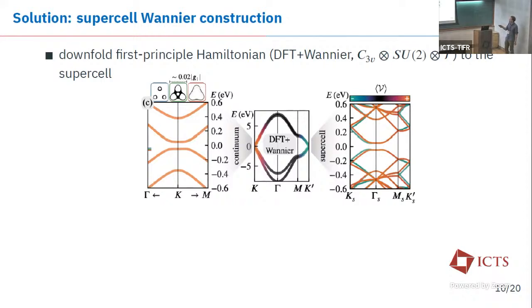So we have rotation symmetries, spin symmetry, and time reversal symmetry, and we just plug them onto the supercell. We get out, compared to the primitive cell, a band structure on the supercell, where you see that all the bands close to the values K and K prime are backfolded to the gamma supercell position. You see a strong valley polarization, shown in red or cyan, in all the energetic region where the low energy physics is, up to a window of roughly 1.2 electron volt. Those states are strongly valley polarized, suggesting that a valley polarized basis is a good way to describe the system.